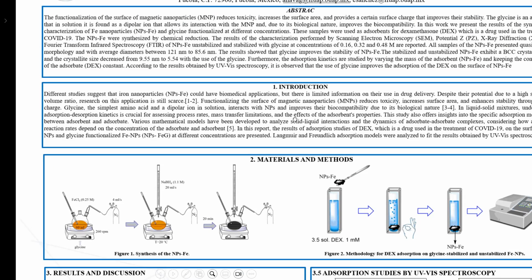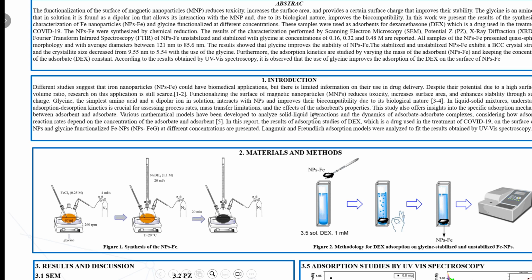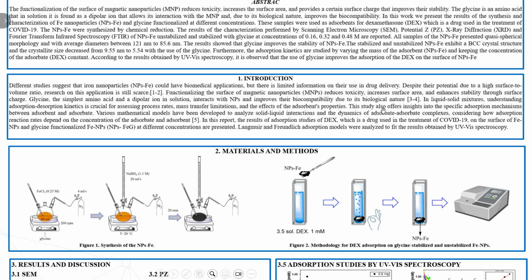Functionalizing the surface of magnetic nanoparticles reduces toxicity, increases surface area, and enhances stability through surface charge. Glycine, the simplest amino acid and a dipolar ion in solution, interacts with the nanoparticles and improves their biocompatibility due to its biological nature.